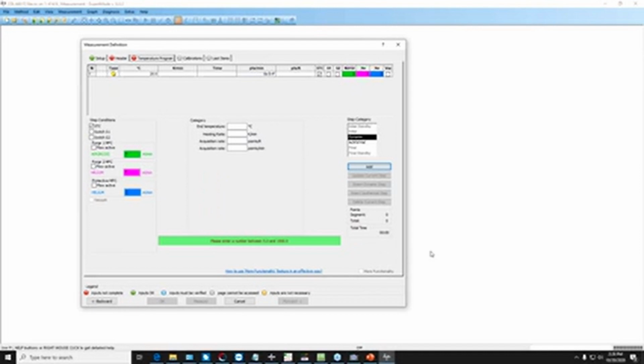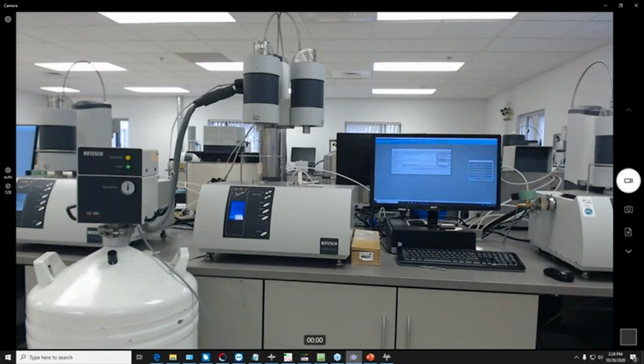Next is what acids to avoid. The acids for cleaning really depend on the materials that you are utilizing. For example, you wouldn't want to use aqua regia for the platinum type crucibles, but if you're using, let's say, HCl, you should be okay. Again, refer to the information in the back of our catalog for some of those cleaning advice.